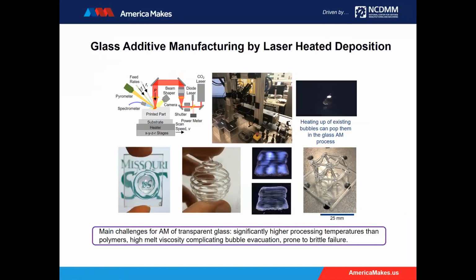My colleague Kinzo was working on glass additive manufacturing, using a laser to melt the glass rod. In fact, he could use more than just one glass rod, and they could have different refractive indices, and you can provide different feeding rates to have different compositions. Therefore, you can make transparent glass with varying refractive index, in addition to making glass artifacts of different geometries, sort of for ornaments.